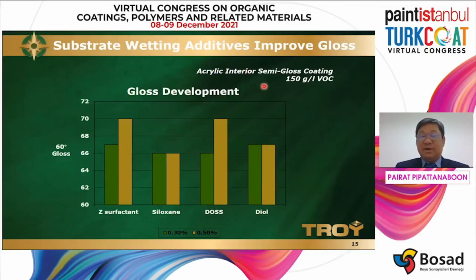Same thing with the decorative acrylic interior semi-gloss coating, low VOC, 150 grams per liter of VOC. We compare with the industry benchmark for the other 3 kinds of chemistry at 0.3%, the green, and at 0.5%, the yellow one: diol, DOSS, dioctyl sulfosuccinate, and siloxane, and Z surfactant. At 60-degree gloss, it improves the gloss development quite a lot, even at a low dosage like 0.3% in the formulation.